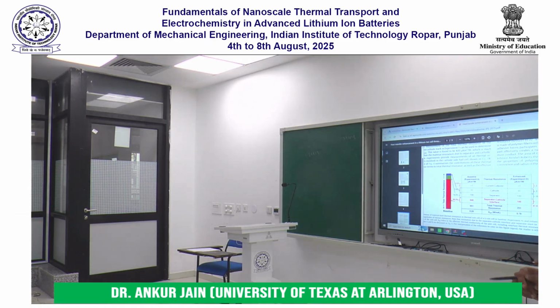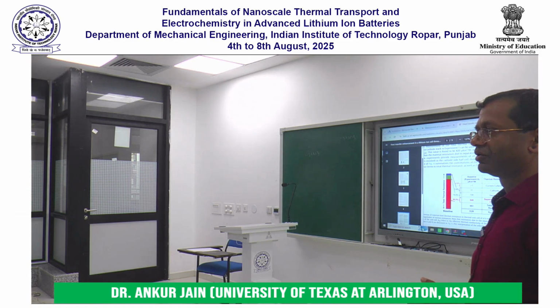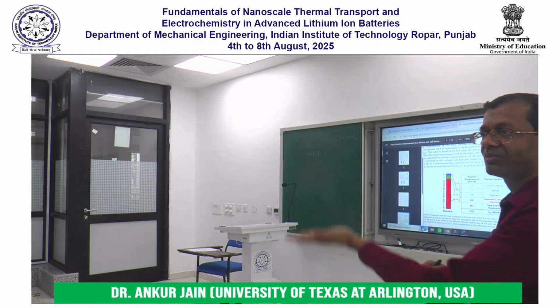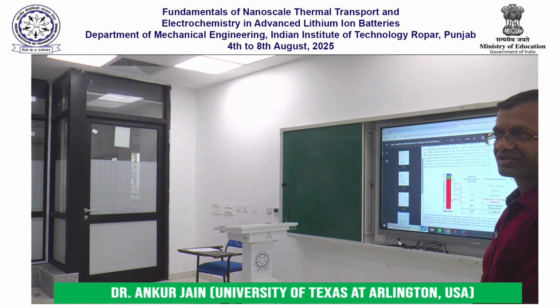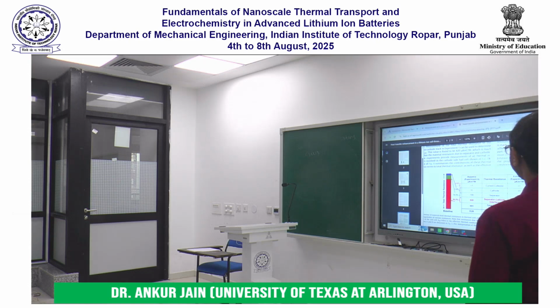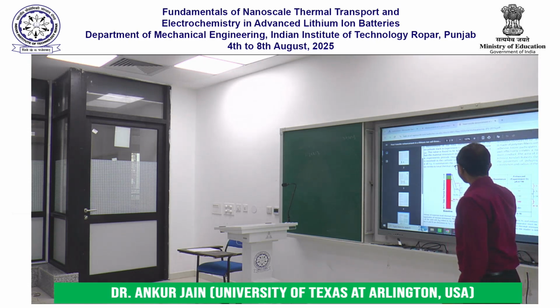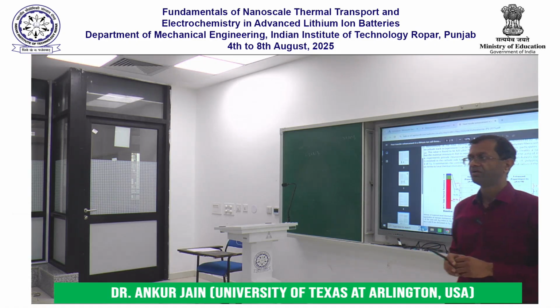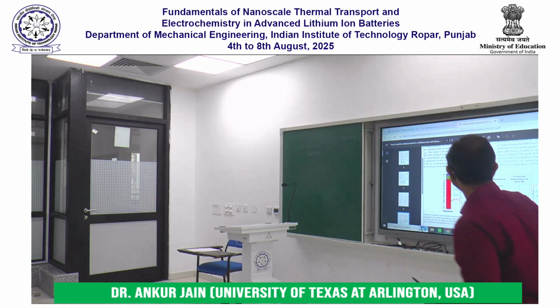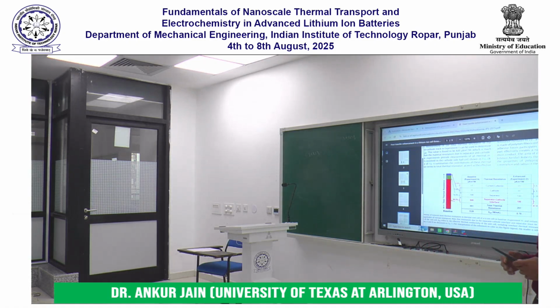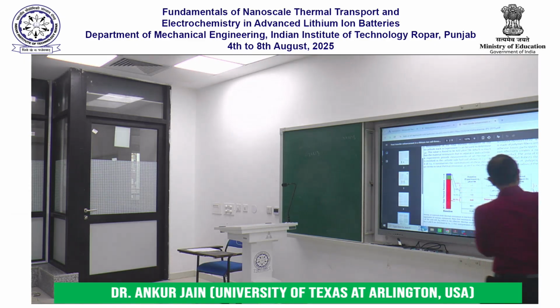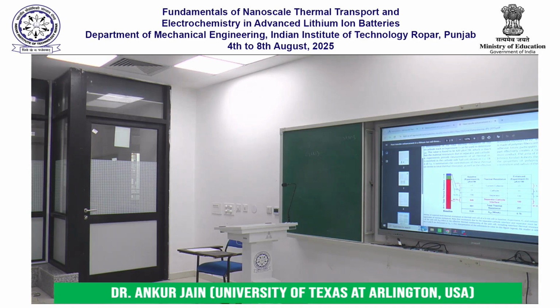It reduces by about 4 times by introduction of that aminosilane molecule between the 2 surfaces. By doing so, I am able to reduce the contact resistance from 840 microkelvin meter square per watt to only 180 microkelvin meter square per watt, because of which the total resistance also comes down quite significantly,